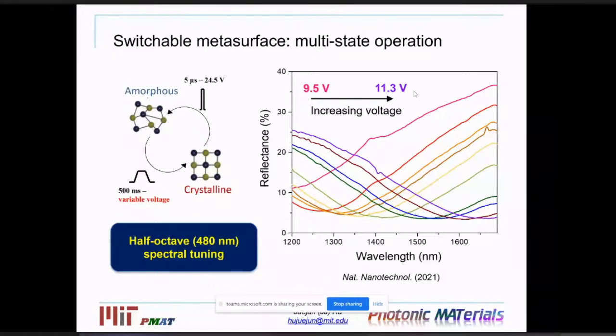But I do want to mention that the cubic and the hexagonal phases are actually quite similar in terms of properties. They are just different stacking sequences of the atomic planes. So how do you ensure it is a cubic phase in your device once it crystallizes? To be honest, on the device level, we have never really tried to verify that. We used Raman to verify that it indeed crystallized, but we did not go one step further to see whether it is crystalline hexagonal or crystalline cubic, partly because we don't care.